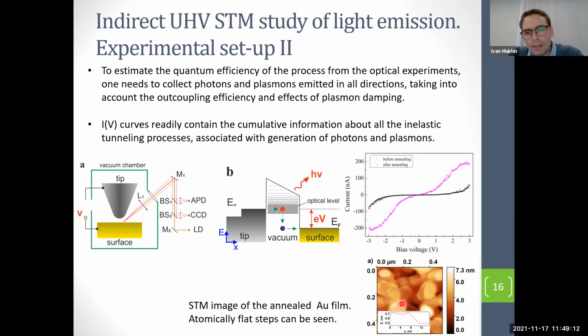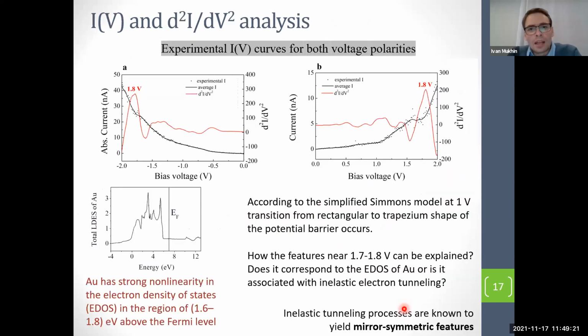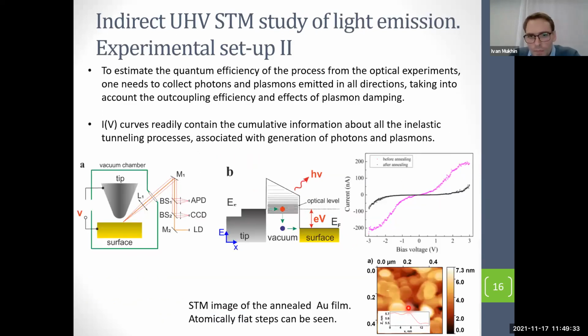Yeah. So we have prepared island gold. This very flat substrate has atomic steps. And what we have done, we measure IV curves between the center of this grain and our STM tip. In that case, due to UHV conditions, we don't need to oscillate. The contact was very stable. And we have studied IV curves for positive applied voltage and negative applied voltage.